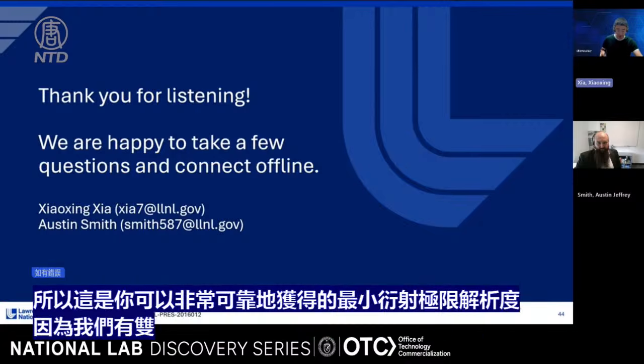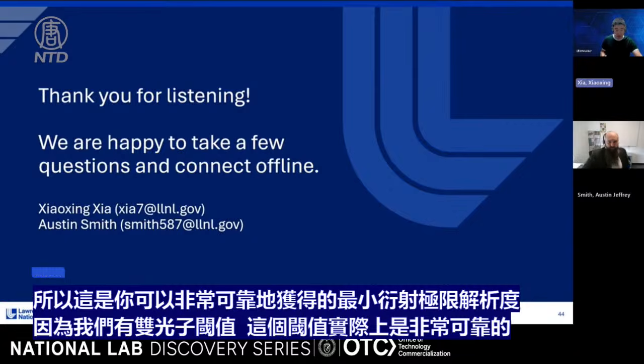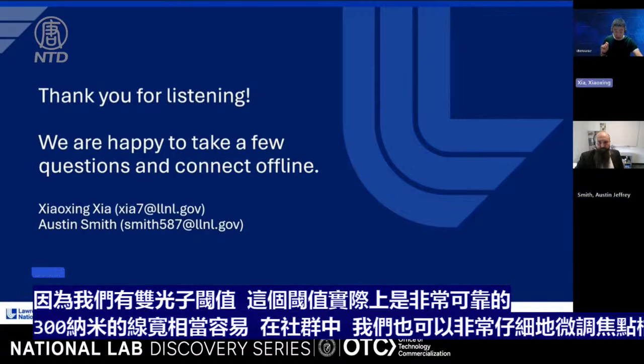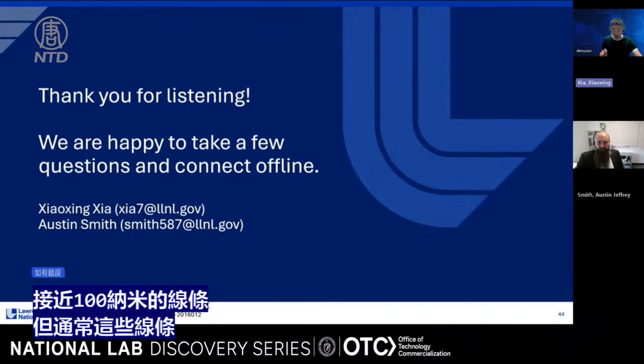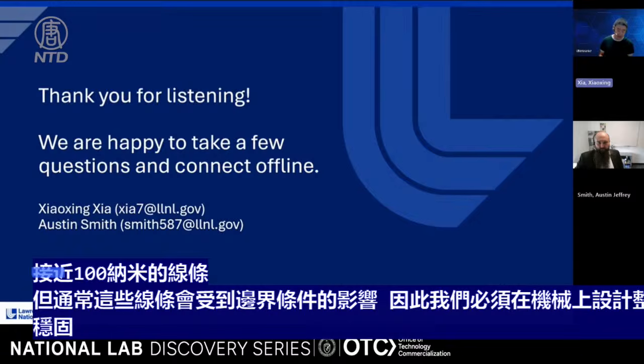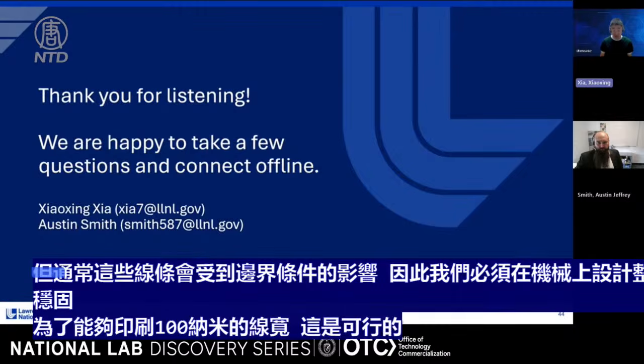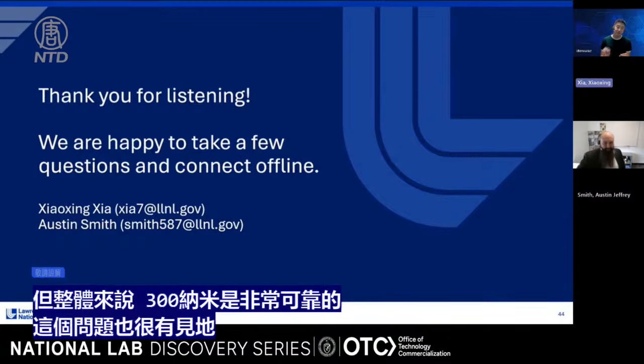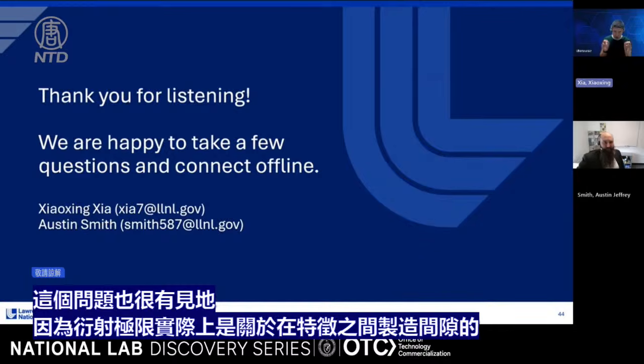Because we have a 2 photon threshold, that threshold is actually very reliable. You can do 300 nanometer line widths quite easily. In the community, we can also fine-tune the focus very carefully to write close to 100 nanometer lines. But generally, those lines are subject to boundary conditions, so we have to design the overall structure mechanically to be very robust in order to print 100 nanometer line width, which is possible. But overall, 300 nanometer is a very reliable value. And the question is also very insightful because the diffraction limit is actually about making the gap in between the features.